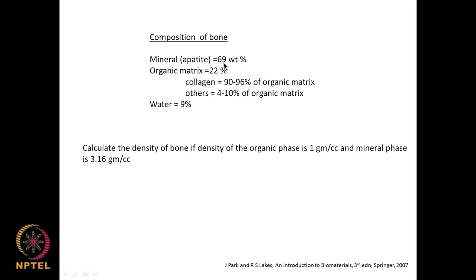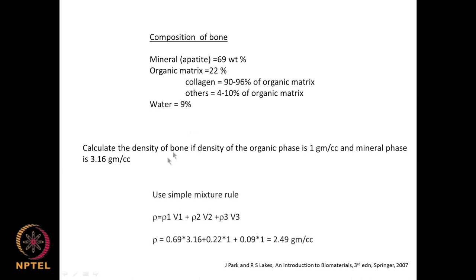We assume the density of the entire bone is a mixture of these components: 0.69 × 3.16 (mineral) + 0.22 × 1 (organic) + 0.09 × 1 (water). The rule of mixtures gives density = ρ₁V₁ + ρ₂V₂ + ρ₃V₃. So 0.69 × 3.16 + 0.22 × 1 + 0.09 × 1 comes to 2.49 grams per cc. So the density of the bone is 2.49 g/cc.